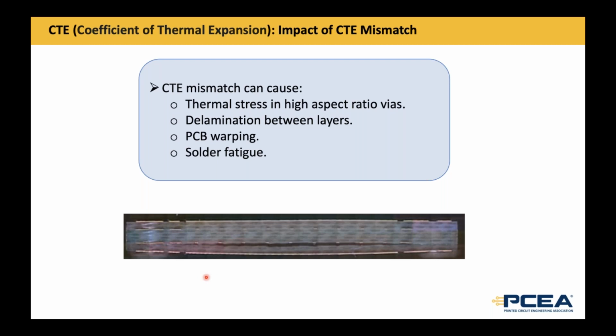So the prepreg on the outside of that inner layer core is different material than the prepreg used to make the inner layer core. And this was a test that was done to evaluate, I think we had about 10 different combinations. This was done outside of Panasonic in a group that we participate in. And our goal is to make a test method that can evaluate these different combinations to see if they work, so that you don't have to build boards before you know that there's a mismatch that might cause delamination. And this test is kind of in the early stages of development, but it is critical because a lot of the newer designs use more than one material. And the industry has a lot of work to do, especially when we start doing a lot of build-up constructions. That's it.